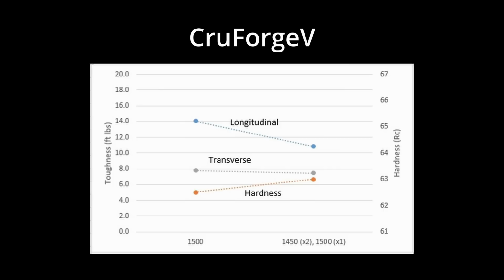But I wanted to bring this up because it is another case of triple quenching where we didn't necessarily see an improvement. And also, when we did this experiment, one of our concerns was, oh, well, maybe it's because we soaked too long, and that's why we didn't see a decrease in grain size and an improvement in toughness. But now we've done it with a salt pot with 1084, and even with much shorter soak times, we did not see an improvement in toughness with a triple quench. So maybe there are certain cases where we can improve properties with a triple quench, but this experiment and the prior experiment with CruForgeV did not demonstrate that.